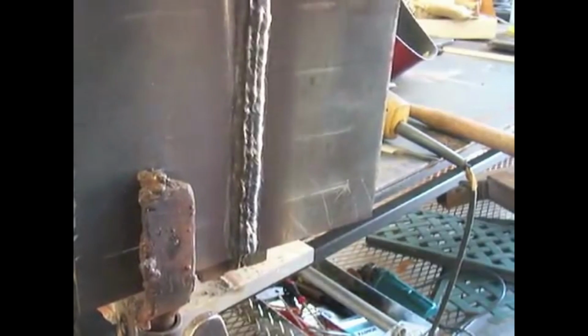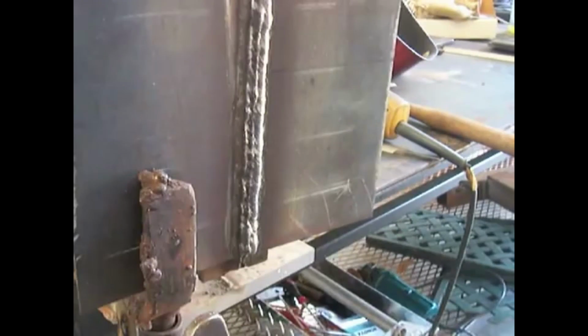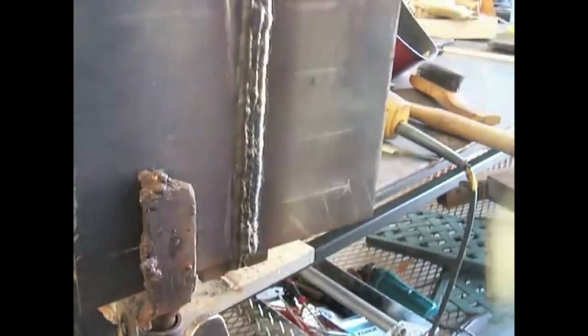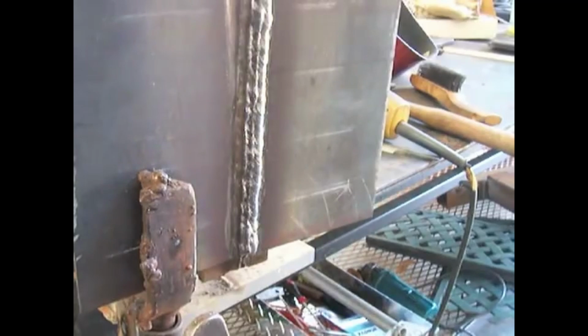Now on the last bead, you want to watch the right-hand side, the side with the base metal, so you don't leave any undercut. There are limitations on undercut on a structural welding test, a plate test like this, on the outside on the base metal. You don't want to leave any on the base metal if you can help it. So that's a three bead cover pass. And clean it up real good. Take a file and scrape those edges and make sure you don't leave any slag. That way you can tell if there's any undercut yourself as you inspect the final weld.